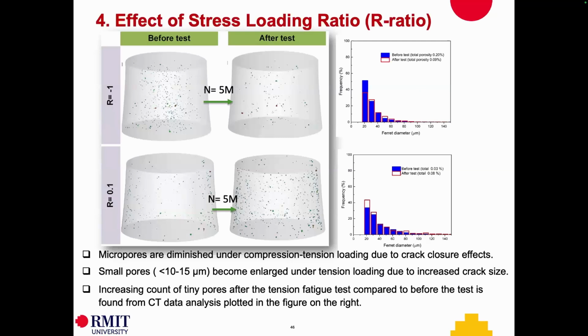So if you have a compression sample, R = -1, you can see compared to this CT diagram, many of the pores are closed and not visible below threshold. Whereas if you have a tension loading, you see a reverse effect. The pores are opening and you get more pores. This is summarized as pore frequency with Feret diameter. As you can see, before the test and after the test, the porosities are reduced. The critical pores, the lower diameter pores, are more reduced. You can see the blue one is the initial and the red one is after compression, after you load it. The lower pores are reduced, whereas it's opposite if you have a tension loading, the blue and the red line, the pores increase in diameter. And that is clearly demonstrated. Increasing count of tiny pores in tension fatigue test compared to before the test is causing the lower fatigue life for tension loading.